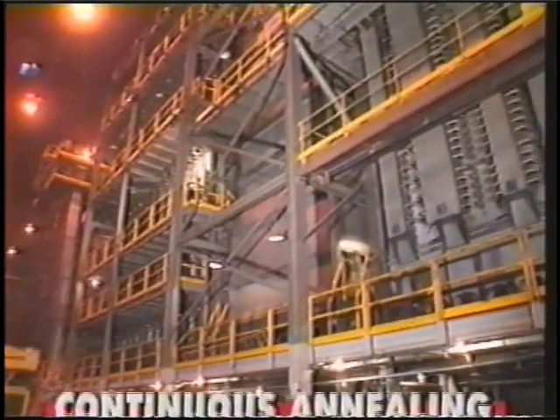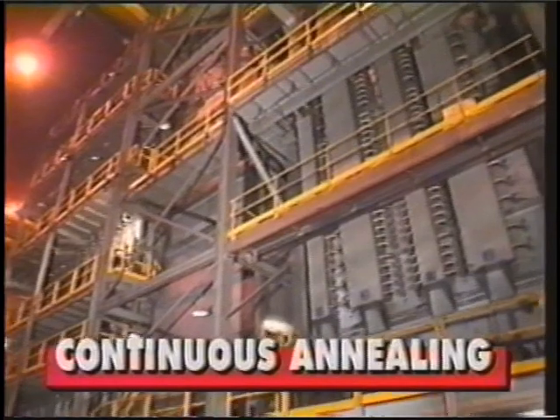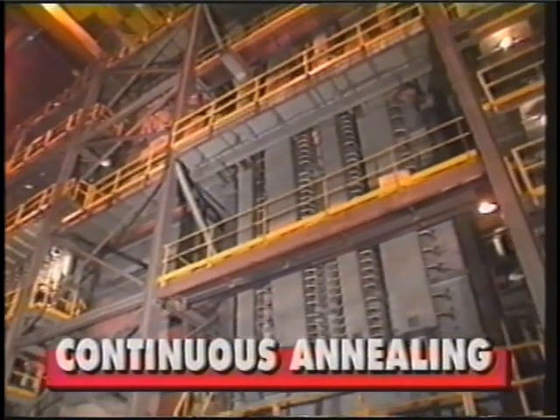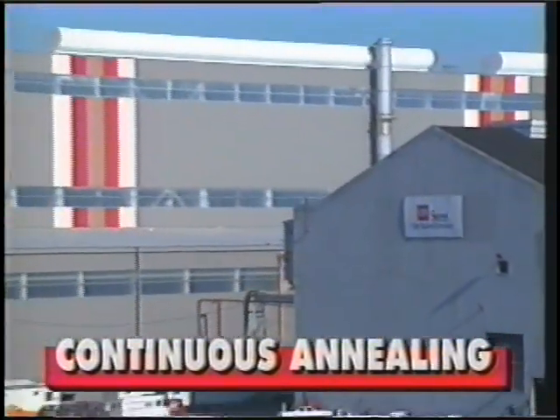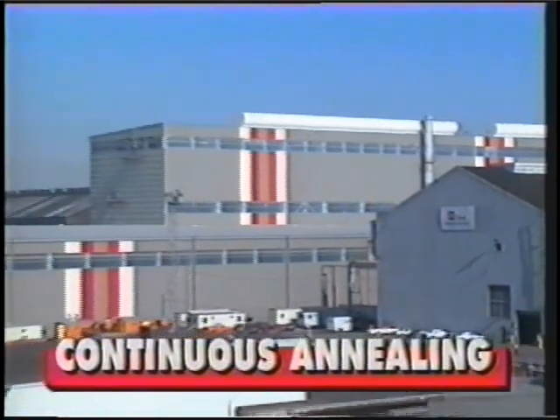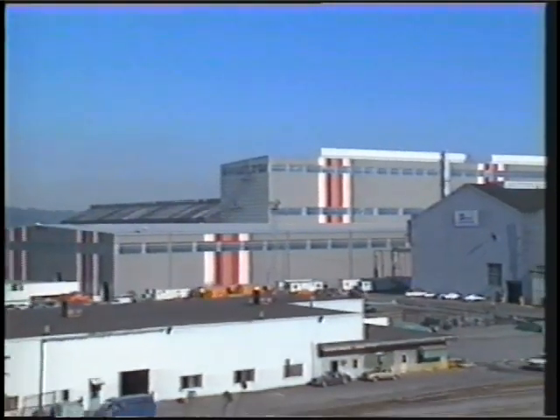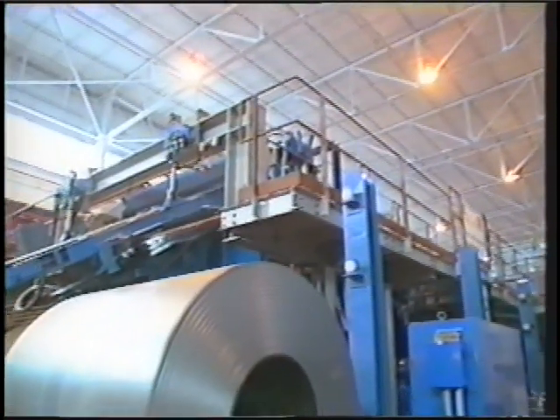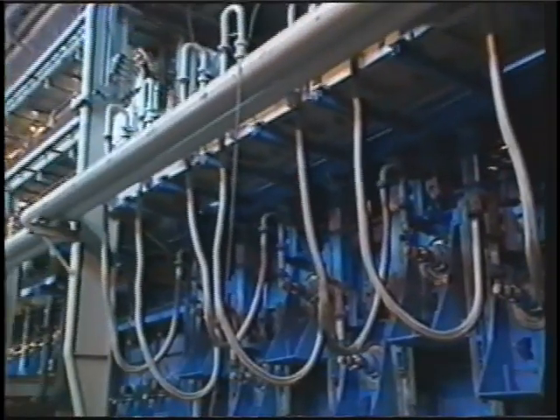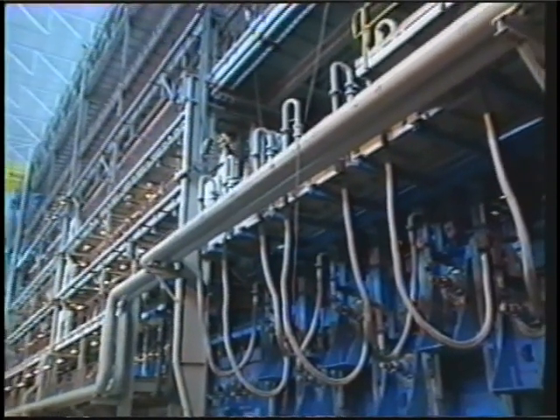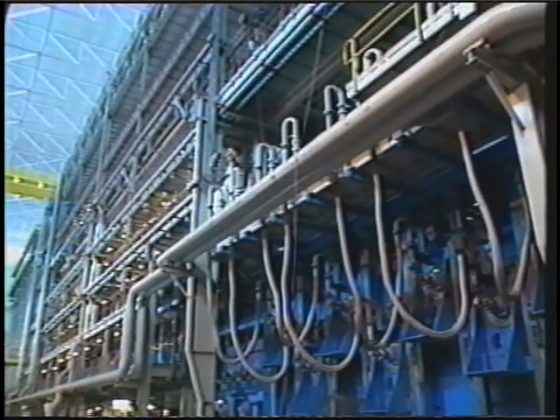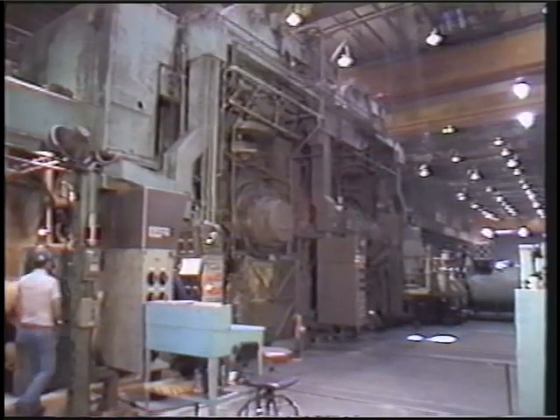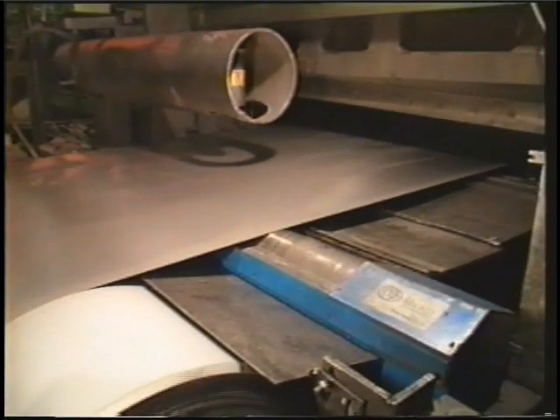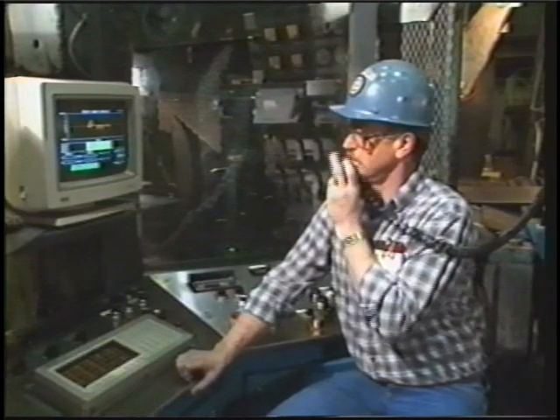The other way is to put the coils through a continuous annealing line like this one at LTV Steel's Indiana Harbor tin mill. At Cleveland Works, a new state-of-the-art continuous annealing line with inline temper rolling is designed to process 75,000 tons of coils per month. The system uses 30% less fuel than the batch anneal process and reduces processing time by at least a week. After annealing, most cold-rolled steel is rolled once again in a temper mill to impart the specified flatness, hardness, and surface texture to the strip.